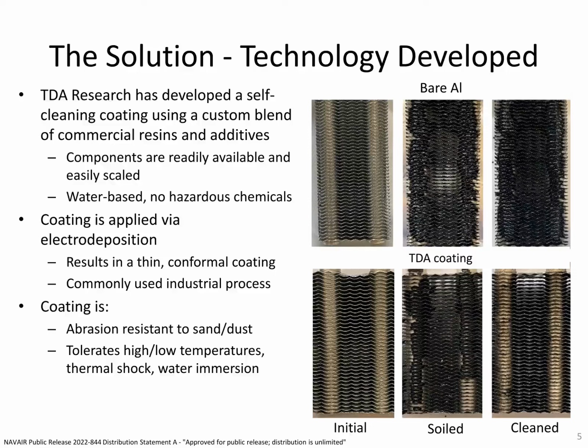We have found that our coating is abrasion resistant to sand and dust. We recently completed external validation testing of this, suggesting that our coating can last up to 1,000 hours in the specified environment. We've also taken our coating through a number of environmental exposures, including high and low temperatures, thermal shock, and water immersion, and demonstrated that the coating maintains both its physical properties and the self-cleaning functionality after these exposures.